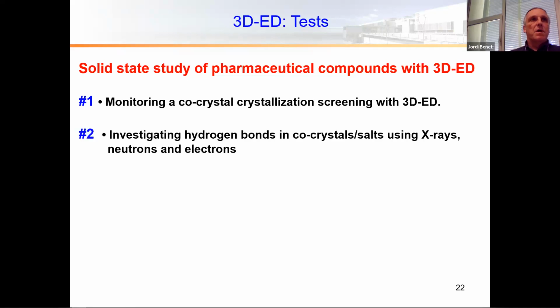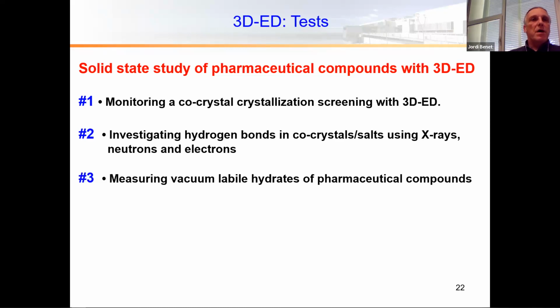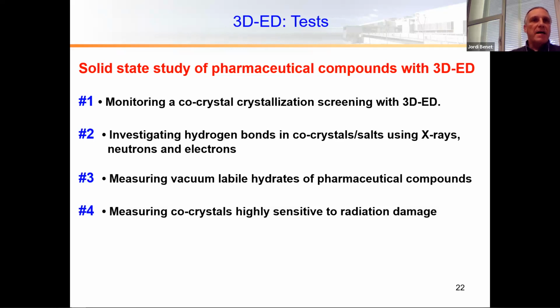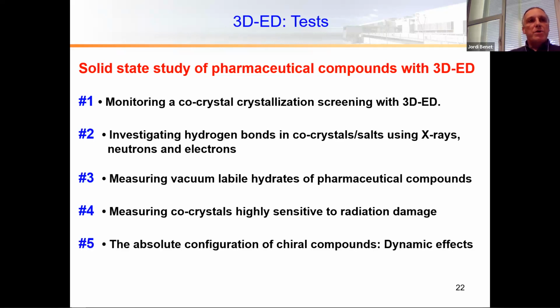We also decided to investigate hydrogen bonds in co-crystals and salts, not only using X-rays and neutrons, but also using electrons as diffraction source. We also tested how it works with vacuum labile hydrates of pharmaceutical compounds. We checked highly sensitive samples in relation to radiation damage. And finally, one very important point: we were using dynamical effects and dynamical processes to determine the absolute configuration of chiral compounds. I will show examples of all these different points during my presentation.